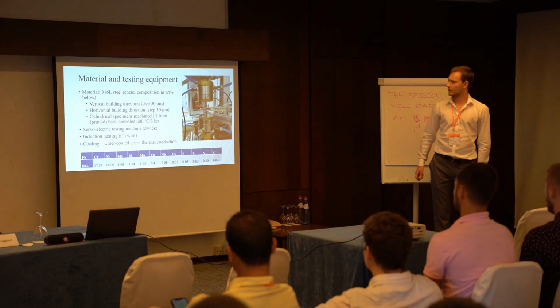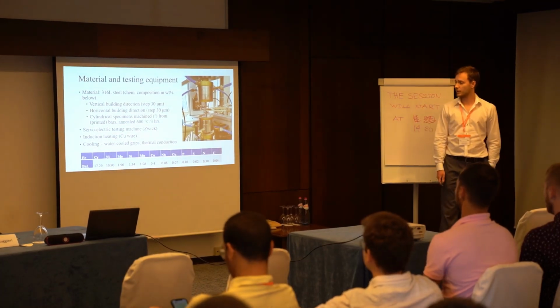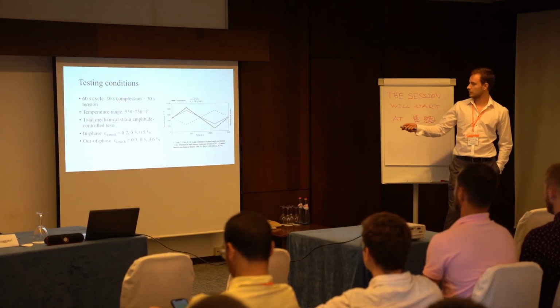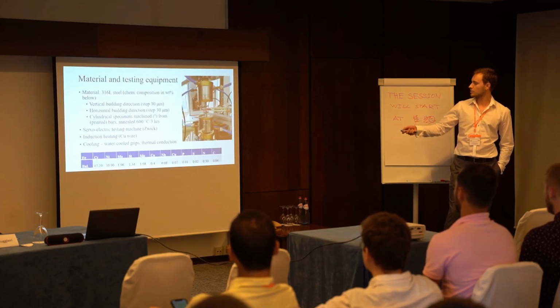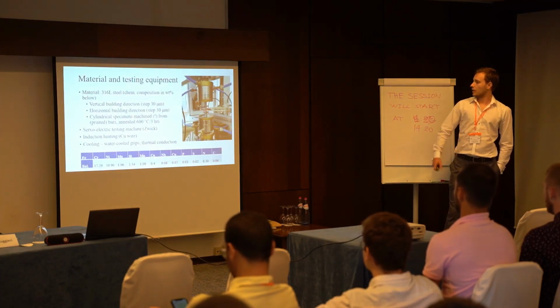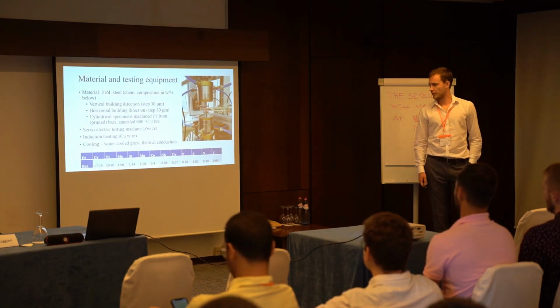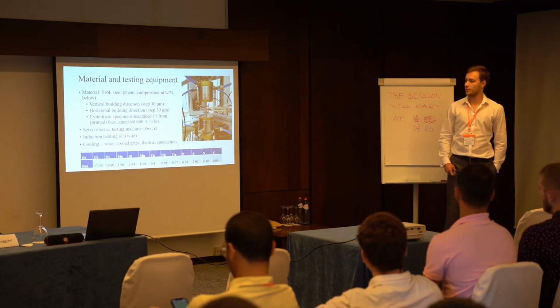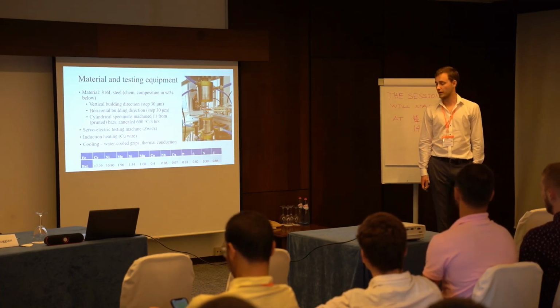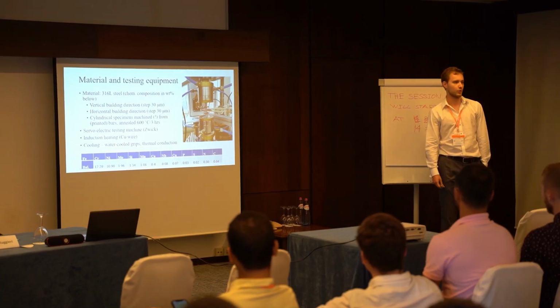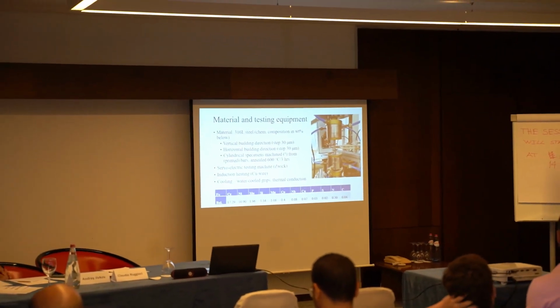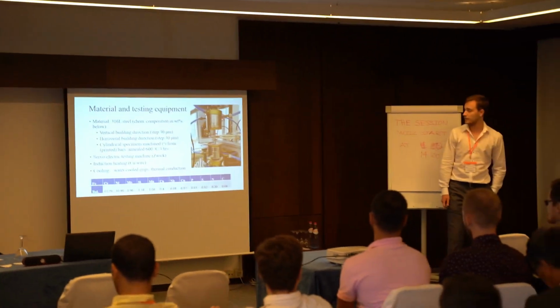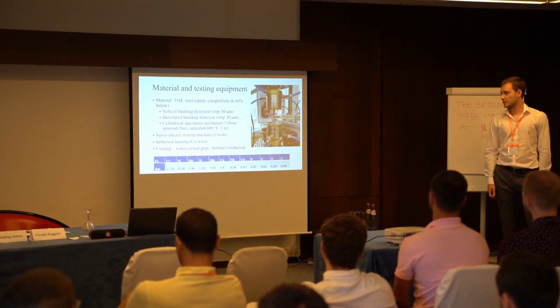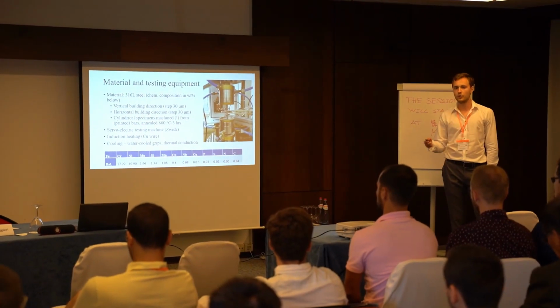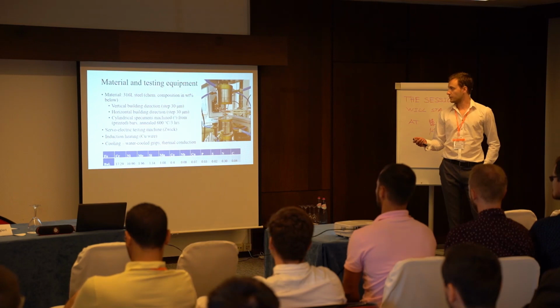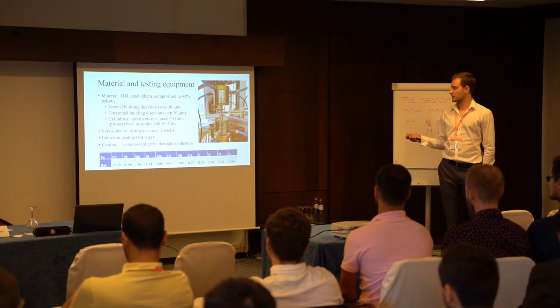So, we study 316L stainless steel with a chemical composition shown below. The material was supplied in printed bars, which were annealed for stress relieving. The technology which was used for printing was SLM, selective laser melting. The specimens were printed either in vertical or horizontal building direction. That refers to the loading axis, basically.